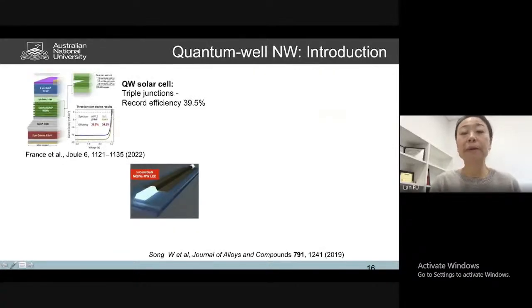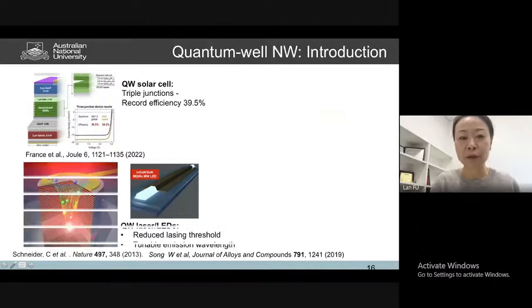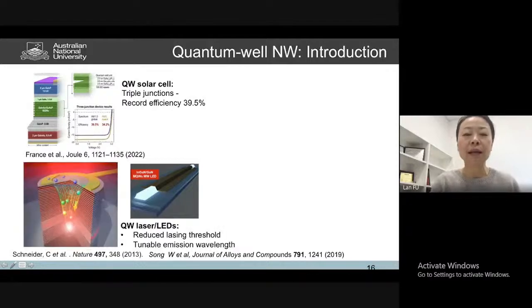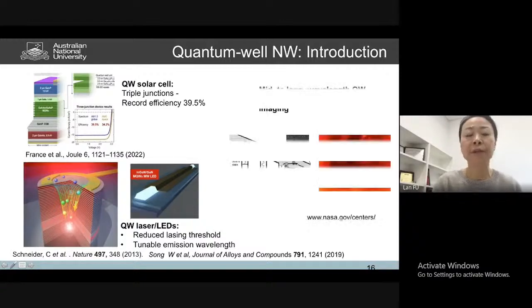So quantum wells are used for a lot of optoelectronics, as I mentioned, for lasers and LEDs. Because of the quantum confinement effect, you can reduce the lasing threshold and also tune the emission wavelengths. Also, by putting quantum wells into a triple junction, record efficiency solar cells have recently been achieved.